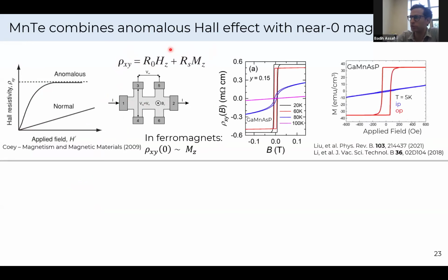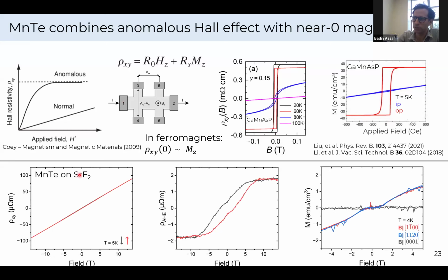And the perfect example to show here is a material that many of us in the community have studied, gallium manganese arsenide with phosphorus, where the anomalous Hall effect has this hysteresis shape that you can see here at low temperature, and qualitatively it's identical to the magnetization hysteresis. Now, manganese telluride turns out to be very different.